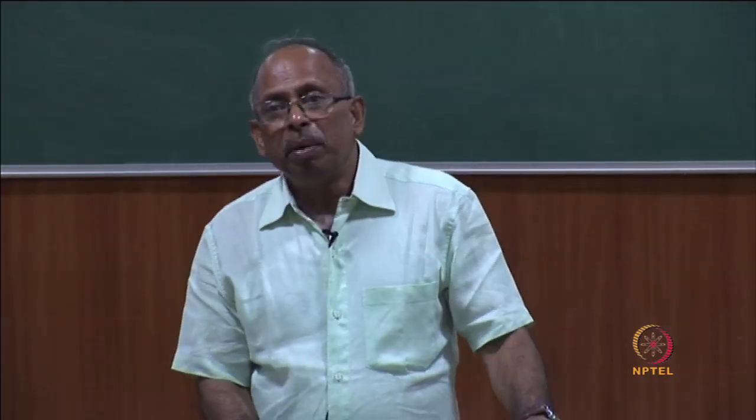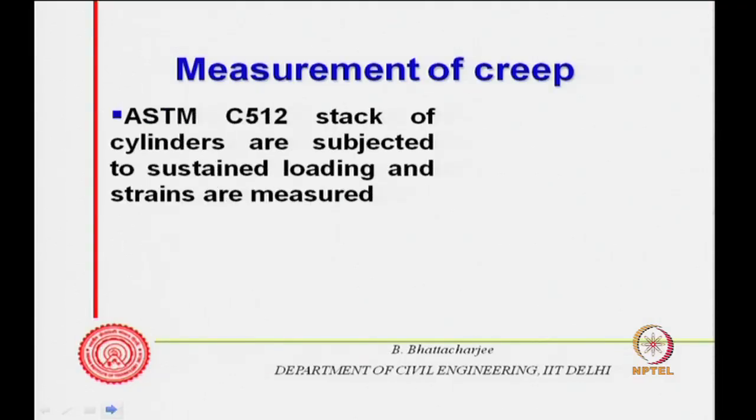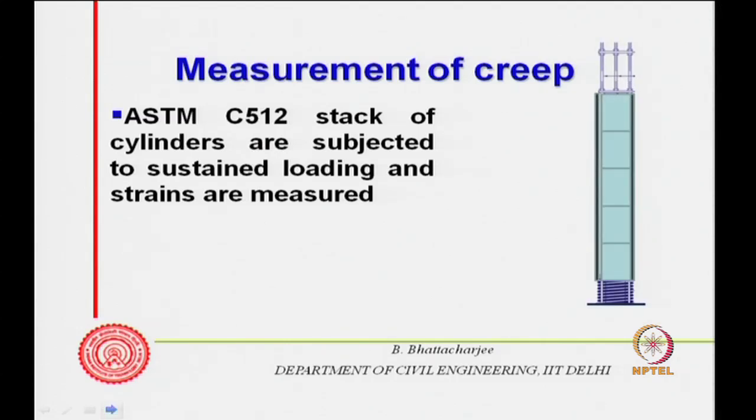So, that is related to prediction of creep, and now let us look into measurement of creep. The only standard perhaps available is ASTM C512, and what it suggests is that you stack cylinders, 4 or 5 of them, subject them to sustained loading, and measure strains. It will look something like this: you have a loading frame, which will have some sort of jack plates, lower and upper, through which you apply load onto the concrete cylinders, and there is a plug in between.